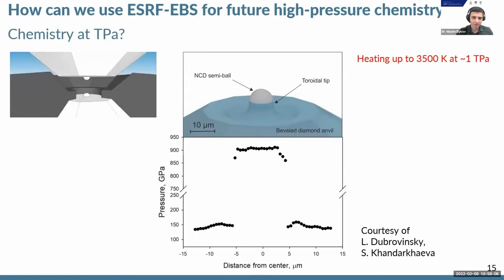So where we are moving to with the upgrade of ESRF is the chemistry at terapascal conditions. So we know by now that we can create pressures close to 1 terapascal, and this is the figure from Leonid Dubrovinsky and Saiana Khandarkhaeva from their new paper, where they combined the toroidal diamond design and double stage diamond anvil design to reach the pressure of about 1 terapascal. And moreover, it was possible to heat the sample up to 3500 Kelvin at 1 terapascal. And what's even more interesting, it was possible to analyze such a reaction mixture which occurred after this laser heating.